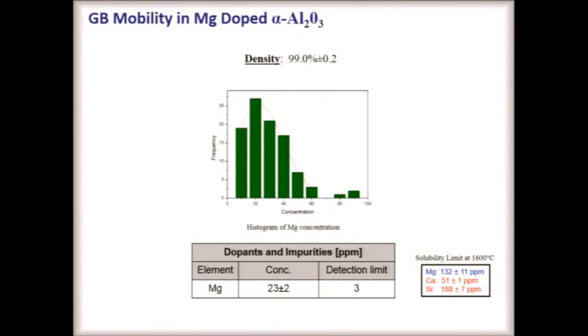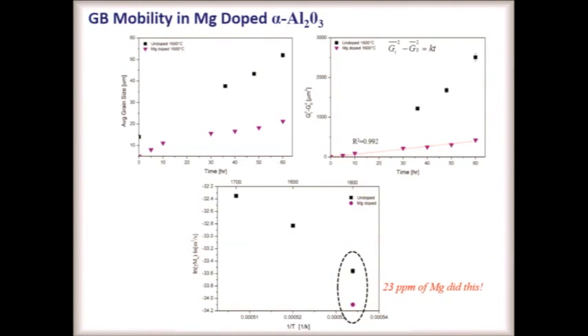What about magnesium doped alumina? I promise you the grain boundary mobility is gonna go down. There's nothing really exciting. We doped, how much is in there? It's not how much we put in. It's how much we measured. And the mean value is 23 ppm. You'll see that that varies a little bit. But it's well below the 132 ppm solubility limit. This is the grain size of the undoped, magnesium doped. This is the parabolic difference. And this is the effective grain boundary mobility.